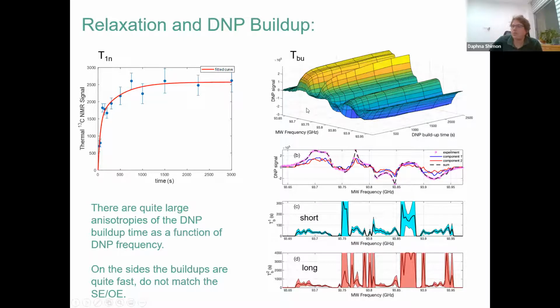we also get something similar. You can see that there is a difference in the buildup times as a function of the frequencies. So if we look at the short time scale and the long time scale as a function of frequency, you can see that in the center, where we see an Overhauser and a solid effect, the time scales are slightly longer than here on the edges, where we think it's an Overhauser effect, but we're not sure.